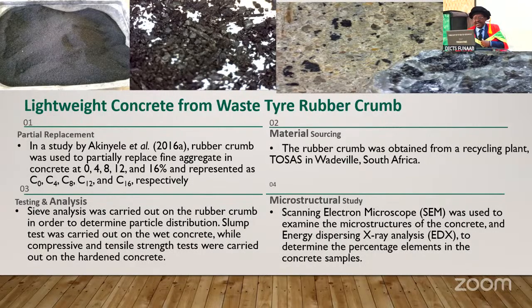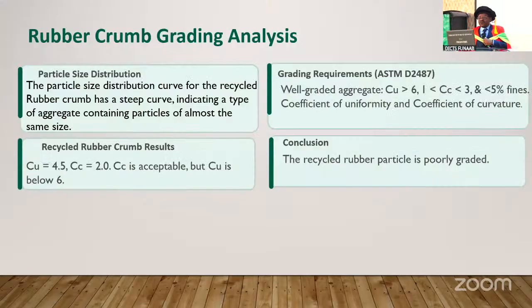The rubber crumb grading analysis. The particle size distribution curve for the recycled rubber crumb has a steep curve, indicating a type of aggregate containing particles of almost the same size. For the grading requirement, according to ASTM D2487, well-graded material must have a coefficient of uniformity greater than 6, a coefficient of curvature between 1 and 3, and less than 5% fines. From our result, the coefficient of uniformity was 4.5, while the coefficient of curvature was 2.0. CC is acceptable, but CU is below 6. The recycled rubber particle is a poorly graded material.